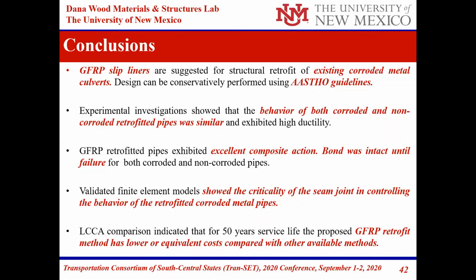Validated finite element analysis showed that the criticality in design of the system is the seam joint, which basically controls the behavior of the retrofitted corroded metal pipes, and which can be taken into account in design. A life cycle cost analysis comparison indicated that for 50-year service, the GFRP method has lower or equivalent cost to the currently available methods of low density polyethylene or high density polyethylene.